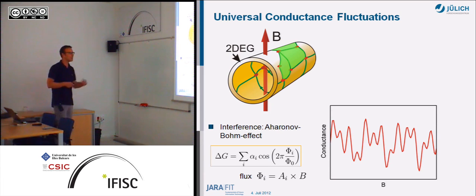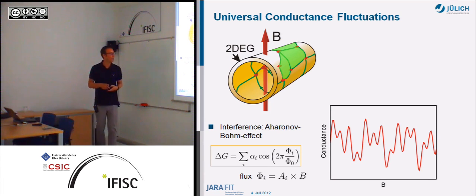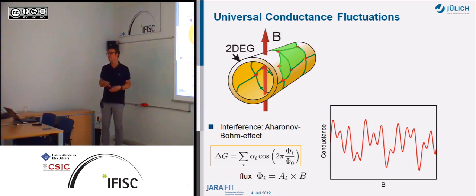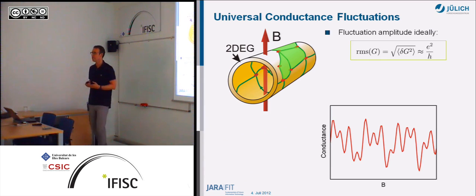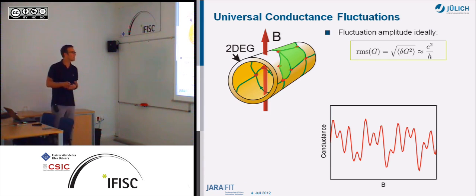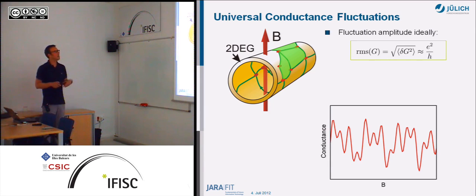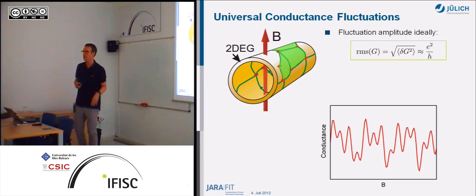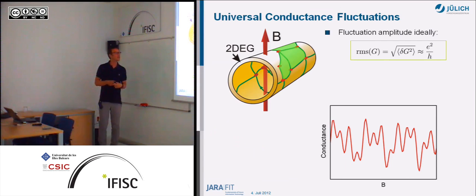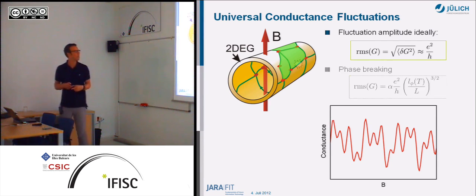You have other areas, and if you look at the end, you see a very messy conductance here, so fluctuating conductance with the magnetic field. And these are the universal conductance fluctuations, which are universal, because if you look at the root mean square here, it's just of the order of e squared over h. So you always end up with this conductance fluctuation if you measure this here.